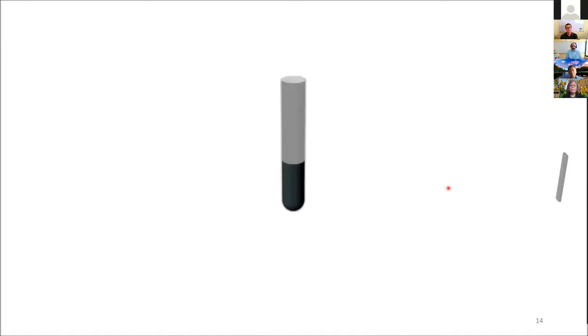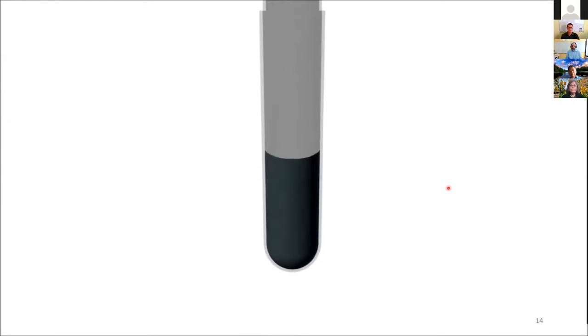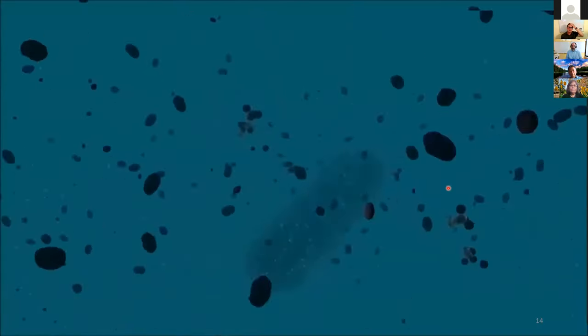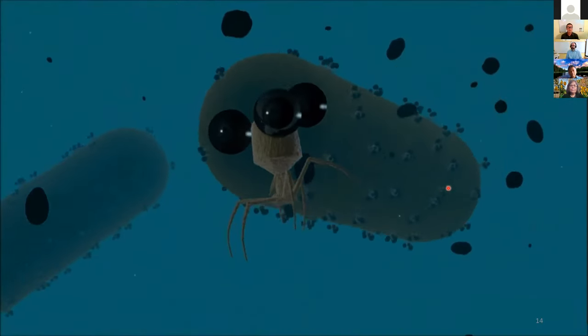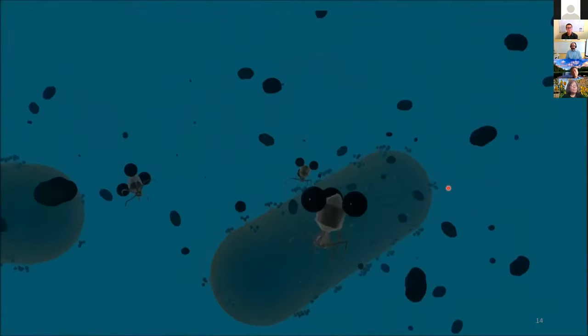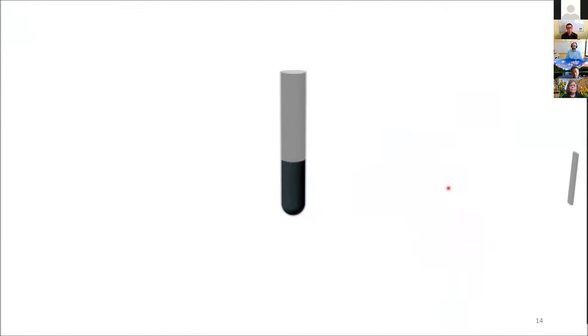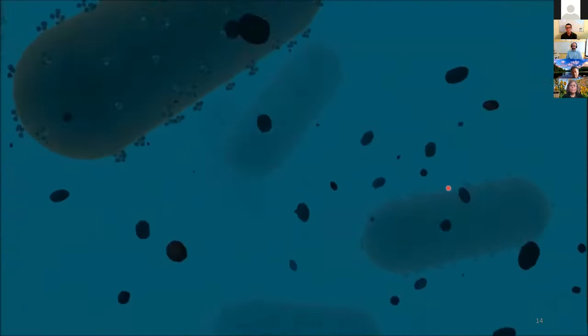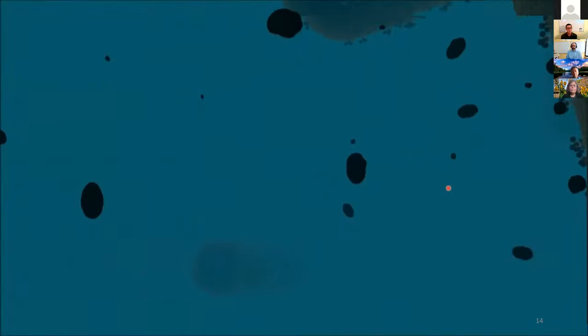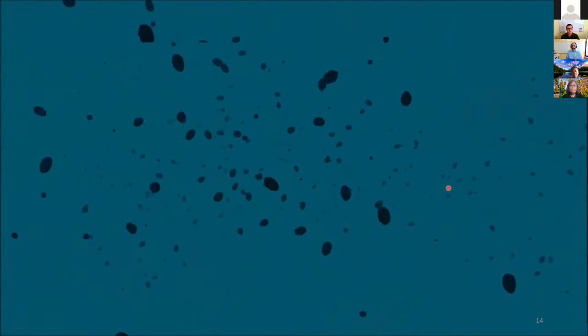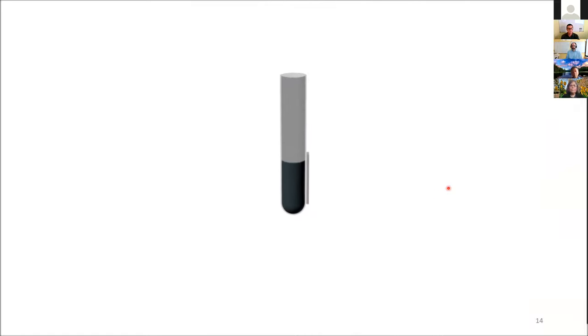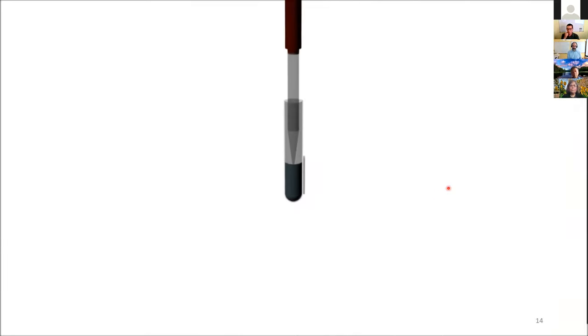If we had a system where we had, say, irrigation water that needed to be detected, that may be a little bit of a problem because filtration, of course, would foul. So we have to look at what if we could just magnetize the phages, something like this, where the phages can bind onto the E. coli. And of course, they're now magnetized. So if we take a magnet and put it by this water sample, we could essentially pull the E. coli out of the water sample, leaving all the particulates behind. We could then aspirate the sample, and what we end up with is, of course, just a concentrated sample containing our E. coli.